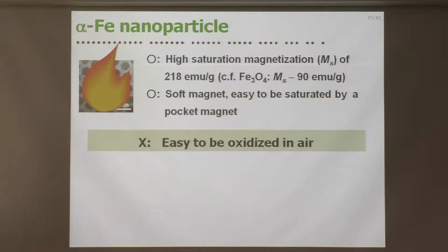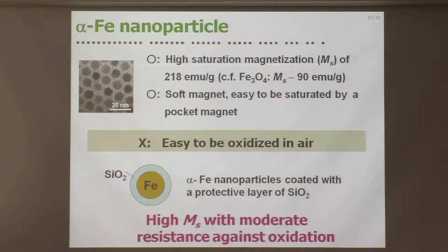There may be several answers. The answer we selected is here: we coat the surface of the alpha iron nanoparticle with some kind of protective layer. If we can realize this kind of structure, we can expect this nanoparticle to have large saturation magnetization arising from the metallic iron core, and moderate resistance against oxidation arising from the SiO₂ shell.